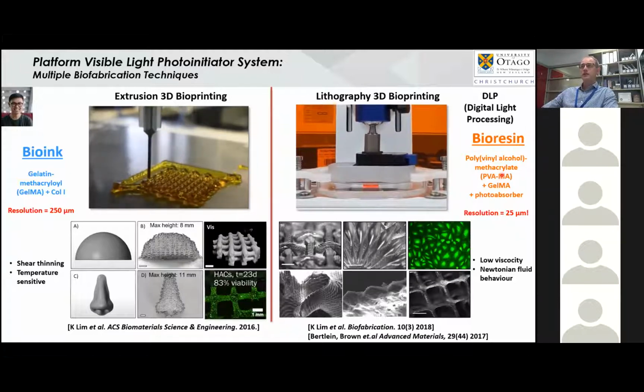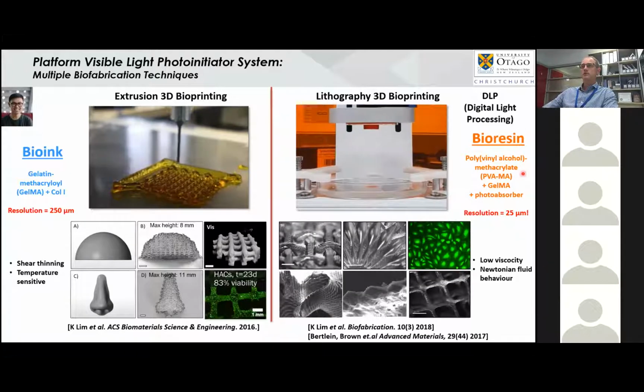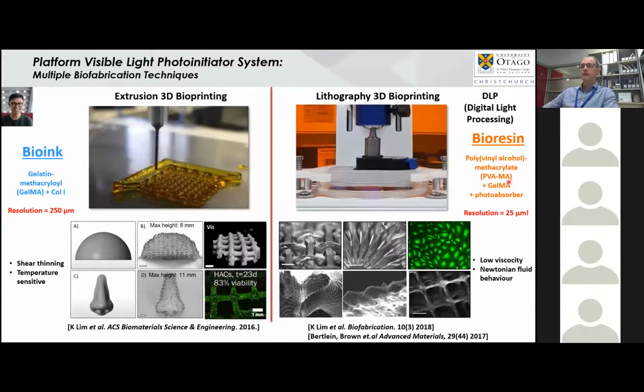So in this case, we started out with a synthetic system for some of the preliminary work we did using PVA, a small amount of GelMA, and also a photoabsorber. And I'd just like to use this opportunity to show the changes in resolution you can get in terms of different biofabrication platforms. So with lithography, we're able to then generate quite complex structures. So like I say, these interwoven features, which you can't easily do using extrusion-based bioprinting.